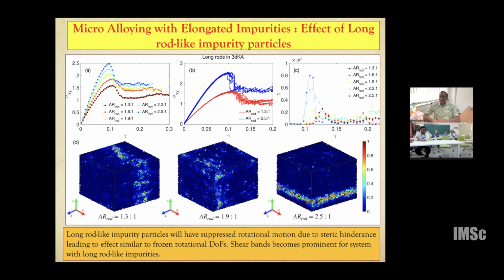Do you allow them to move or not move when you shear the sample? In this scenario, they are free to do both rotation and translation. But just because they are elongated, their rotations are hindered very, very significantly. The aspect ratio here is around 2.5. It's not very long, but it is 2.5 particle diameters.